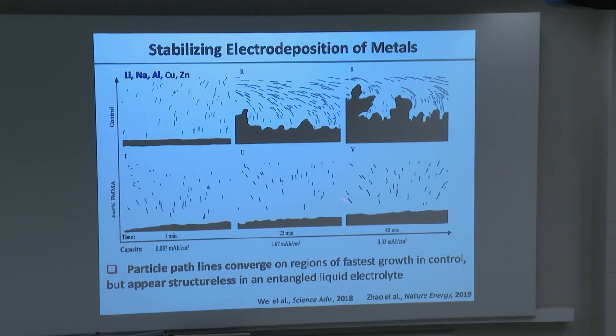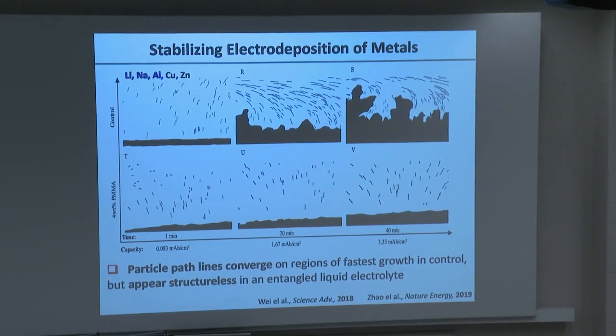In the case of electrolytes with polymers, you notice something very different. The growth is not completely flat, but more uniform than in the case without polymers. And what we also notice, if we monitor the tracer particles, there's this gentle rain. They just come down uniformly across the surface, indicating that the polymer is able to provide uniformity in the deposition.